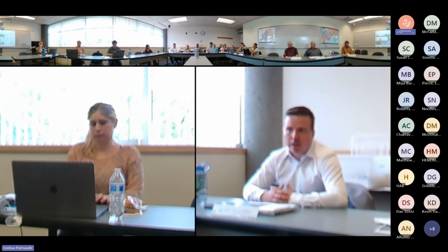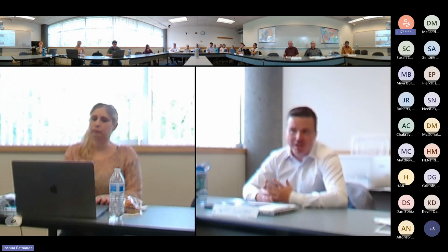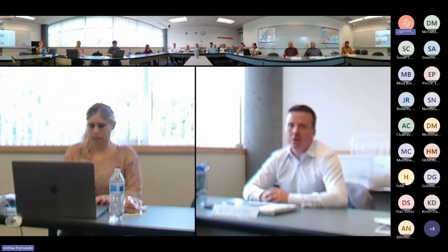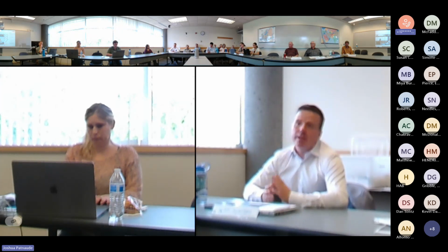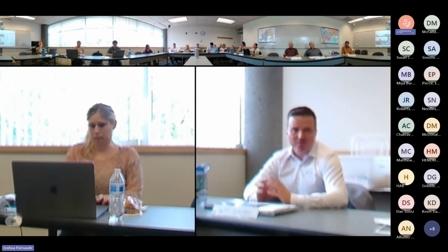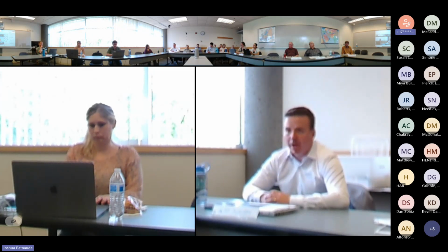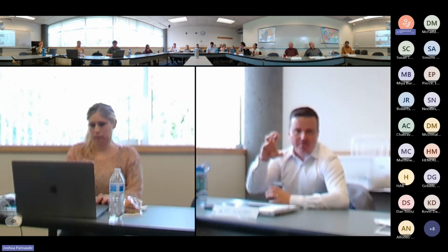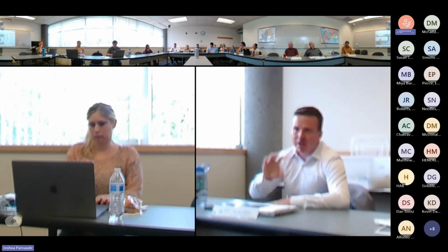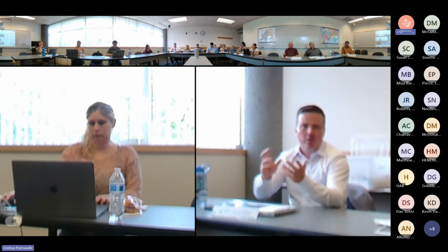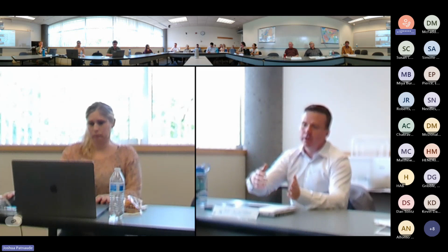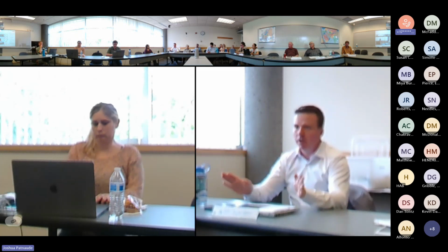So there's another collaborative work between us and SRNL where we acknowledged that potential challenge and screened a number of different formulations. And in that work, using cast stone, our most studied formulation, you mix it with that ETF brine, it sets, but very soft. And if you get it to set by pushing the calcium ratio, it'll kind of crack and crumble because your calcium to sulfur ratio is completely thrown off.